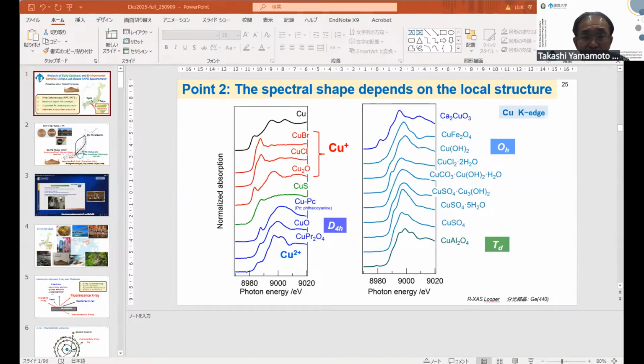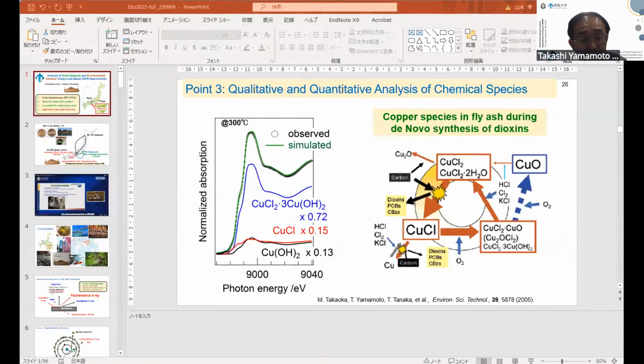We can know the candidates of the unknown samples. This is one of the results. With XANES spectra, qualitative and quantitative analysis of unknown species is possible. And this is the in situ XANES spectra of copper in fly ash during the de novo synthesis of dioxins. This is 300 degrees combined with the fly ash.